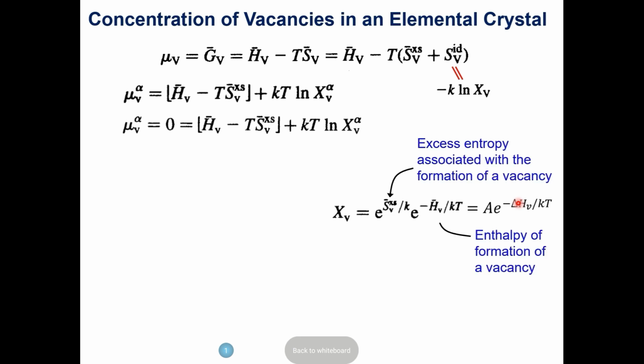Okay, so I already talked about this. And if you take the logarithm of that term, the entropic term will look like this, and the temperature term will go as 1 over T. So if you plot logarithm of vacancy concentration versus 1 over T, you get a straight line.